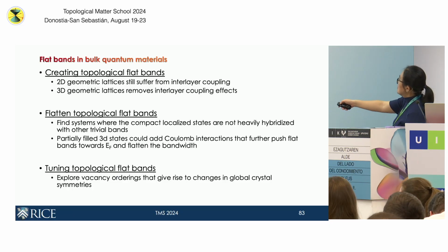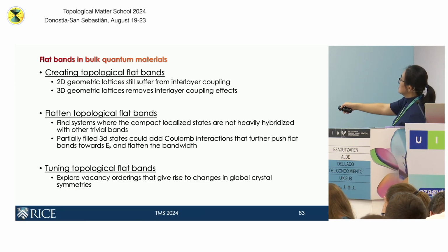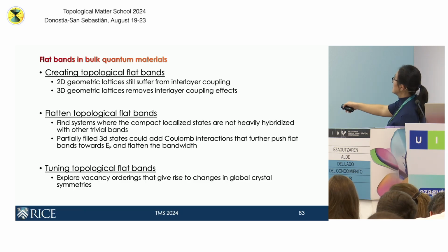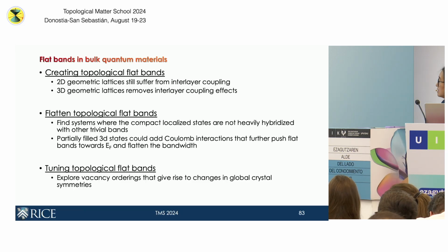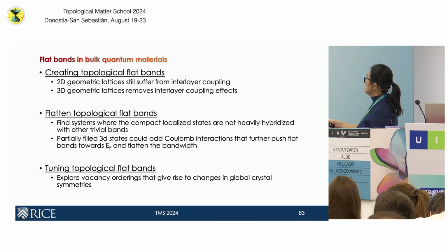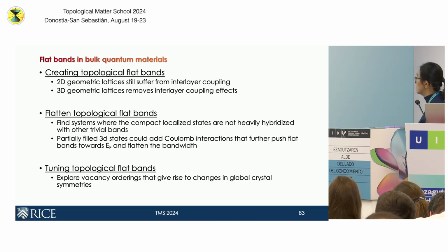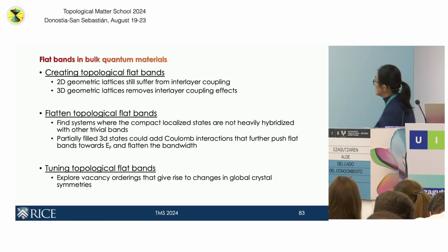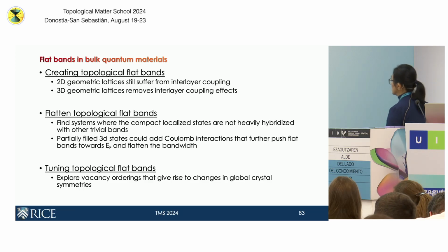How do we find topological flat bands in bulk materials? We can think about 2D lattices, and then even going to 3D, which removes this interlayer coupling. And then we can think about systems where those compact localized states are not so much hybridized with the rest of the other bands. This will preserve the flatness of the flat band. And then also think about looking for systems that have partially filled 3d states that could potentially have stronger correlation effects that would further enhance the correlation in the system already produced by the topological flat band. And it considers things like vacancy ordering that can be used to switch these flat bands on and off, right?